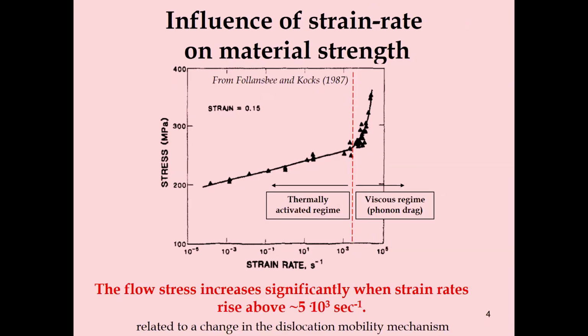So the influence of strain rate on material strength is a complex issue. And if we could see here, this is a result from a paper by Follansbee and Kocks looking at copper. And we could see the strength of the material as a function of strain rate.